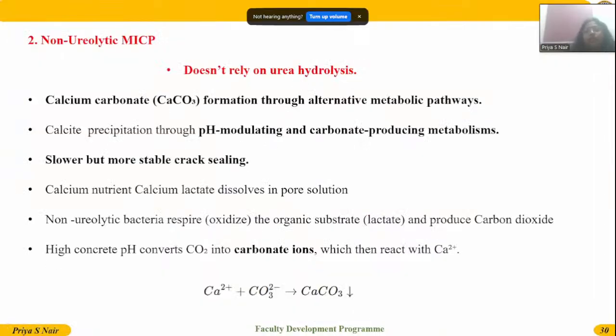The next is non-ureolytic. In that case, it does not rely on urea hydrolysis, as the name itself says. Calcium carbonate forms through alternative metabolic pathways: calcite precipitation through pH modulating and carbonate producing metabolism. It is a slower process, but gives more stable crack sealing. Calcium lactate, the calcium nutrient, dissolves directly in the pore solution. Non-ureolytic bacteria respire the organic substrate and produce carbon dioxide. The high concrete pH converts this carbon dioxide into carbonate ions, which then react with the calcium ions to form calcium carbonate. So the mechanism is different for both.